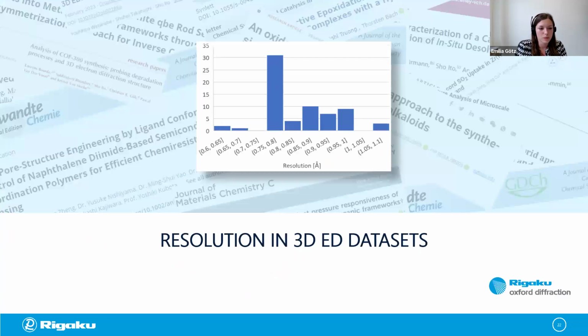Another thing that we can have a look at is the resolution. The resolution of most datasets was around 0.8, which makes sense since this is the resolution that is required most of the time. Of course, some structures did not diffract that strongly, so the resolution had to be cut, but still the structure could be solved.